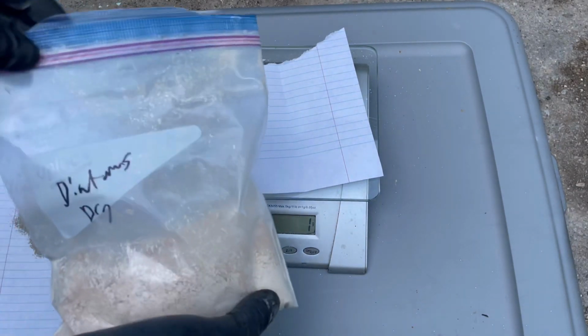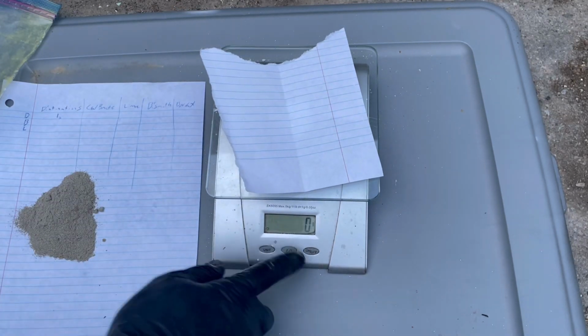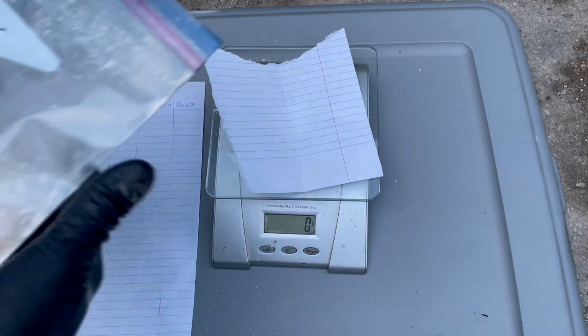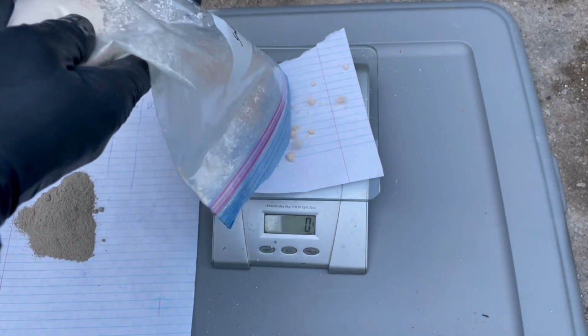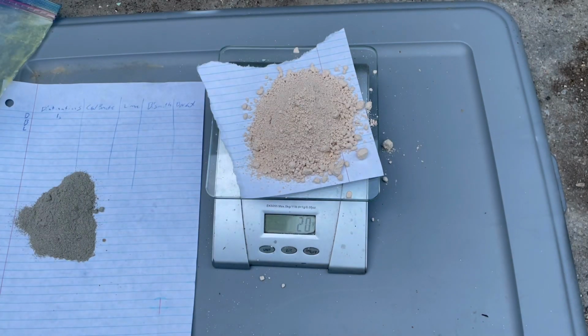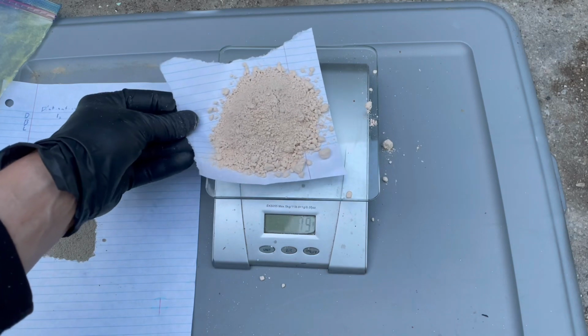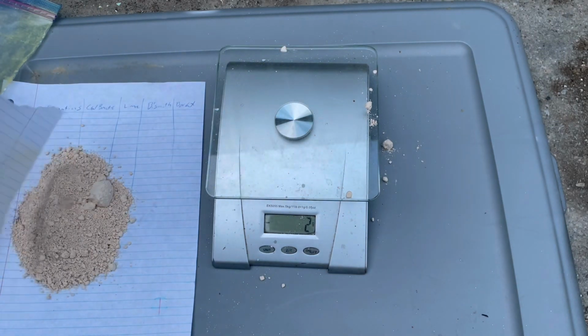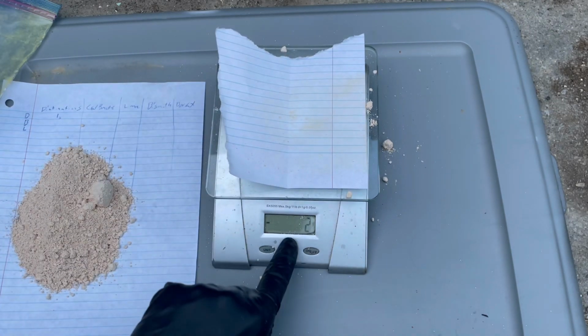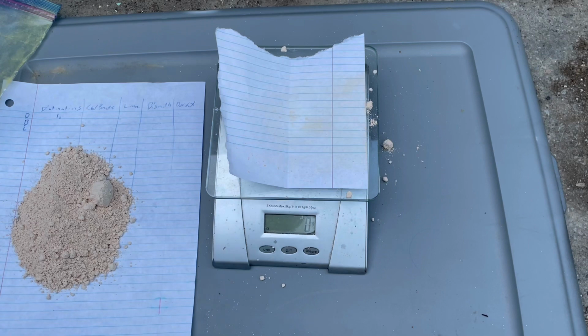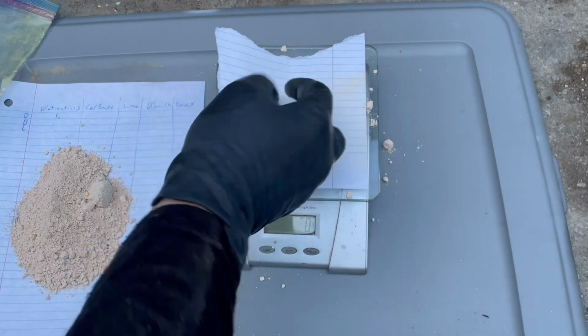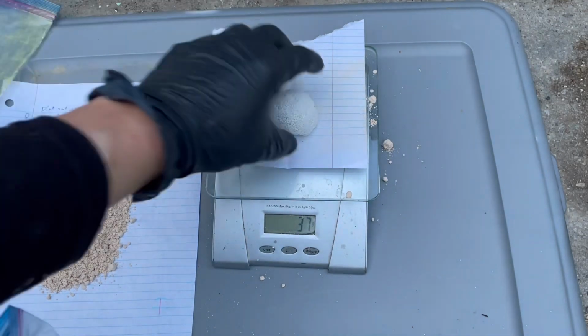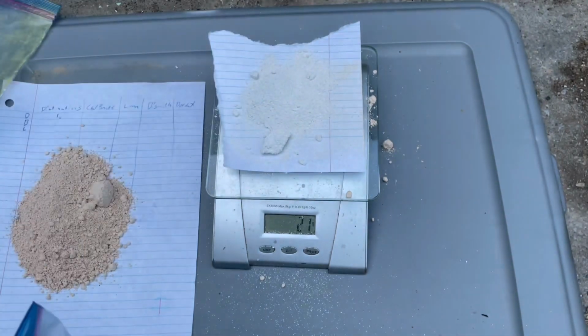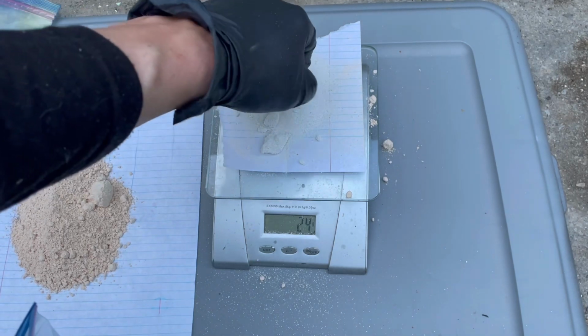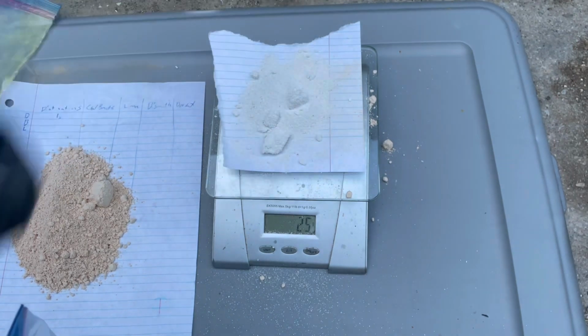For this one, we're definitely going to need the silica. In fact, I'm going to weigh out 20 grams, so pretty much the whole weight of the sample. There's 20 grams. It'll pack down. Add that to my ore sample. I'm going to do another 20 grams of the soda ash. Actually, let's go up to 25. A little bit more. There we go.